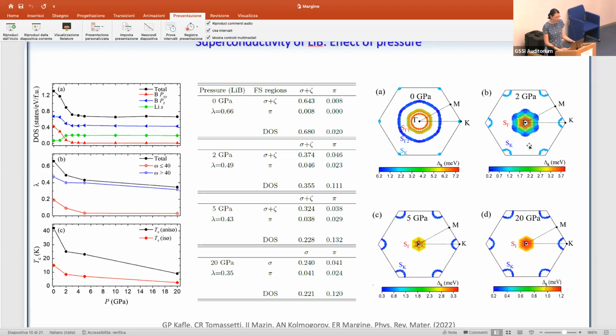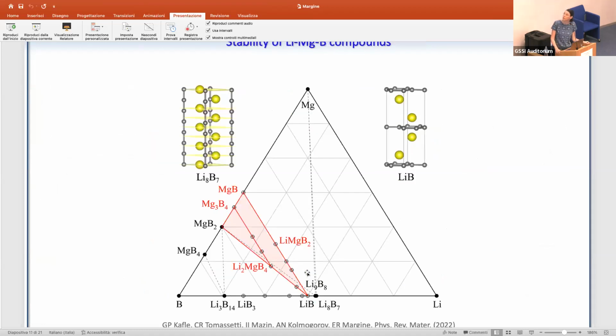These changes are also reflected in the anisotropic gap. I'm not showing it here, but you can figure out from this crossing that the two-gap or multi-gap structure is preserved, but above 5 GPa, there is no contribution from the nearly free electron states. Then the contribution from the sigma states is really diminished. And while there is some contribution from the pi states, this still remains insignificant. As you can see from this two-band decomposition model, the highest contribution to the coupling still comes from the boron sigma state.